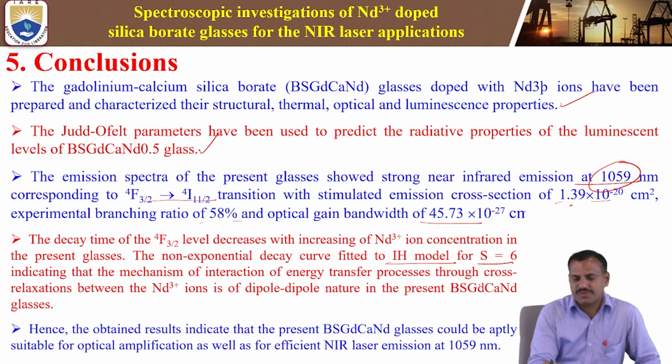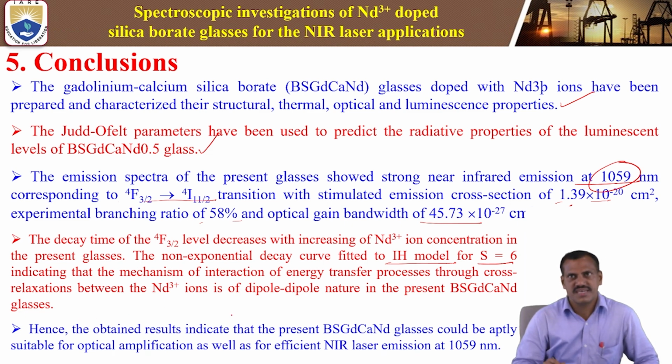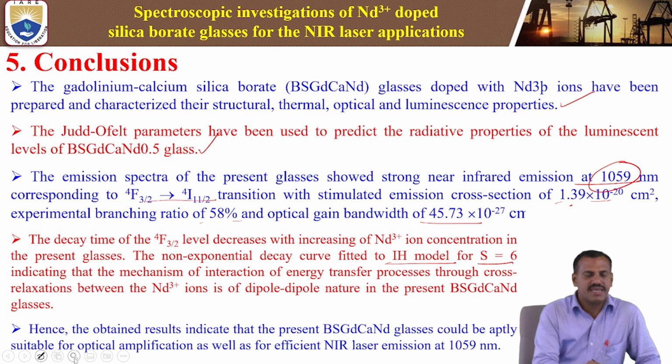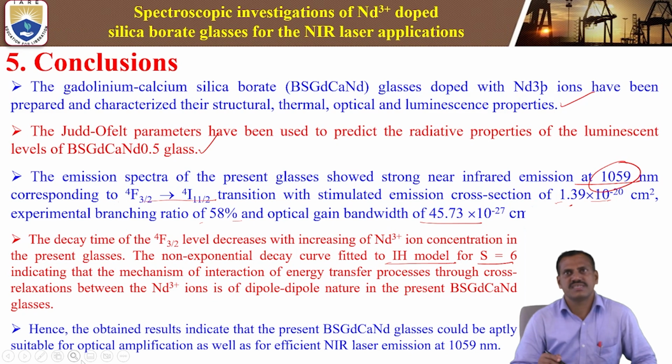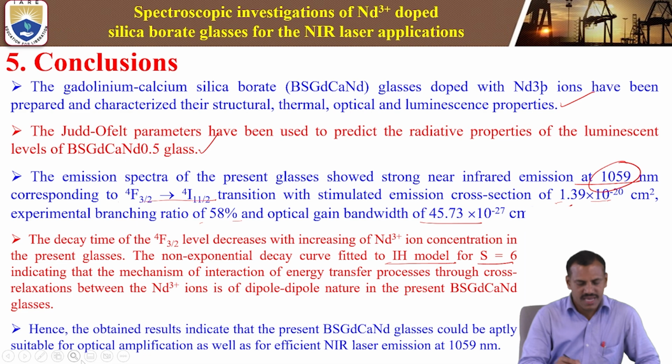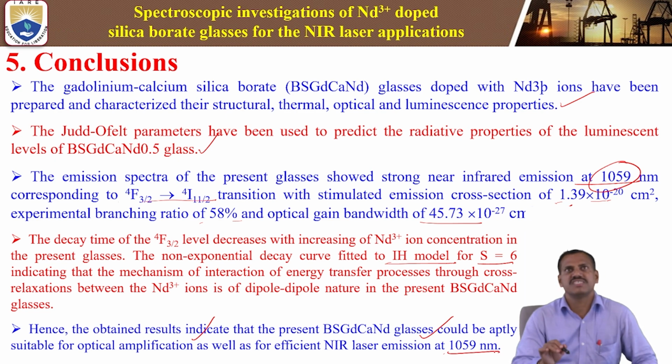So the energy transfer process through the cross relaxation channel between the Nd3+ ions is dipole-dipole in nature in the present Nd3+ doped gadolinium calcium silicaborate glasses. Finally, the obtained results indicate that the present glasses could be suitable for optical amplifiers as well as for efficient NIR laser emission, particularly at 1059 nanometer. That is why, in our present study, the glass is useful for near infrared laser applications. These are the conclusion or summary of the present Nd3+ doped silicaborate glass systems.